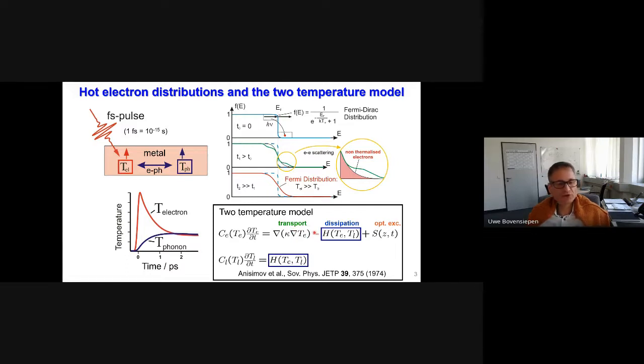If you solve this equation for typical metals, transition metals, for example, what you find is that the temperature on the vertical axis, as a function of time, which is given here in picoseconds, has this behavior where the electronic temperature shoots up very high. This has to do with the small electronic specific heat that is included in the model. And then the cooling of this hot electron temperature by electron-phonon coupling increases the lattice temperature, and within a few picoseconds, the two temperatures have equilibrated.